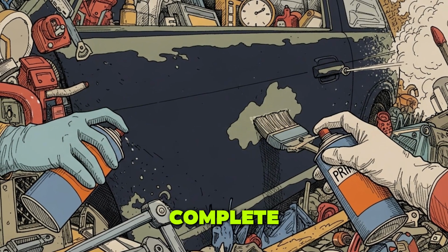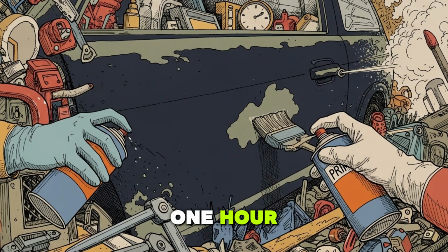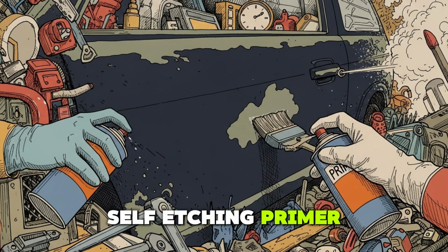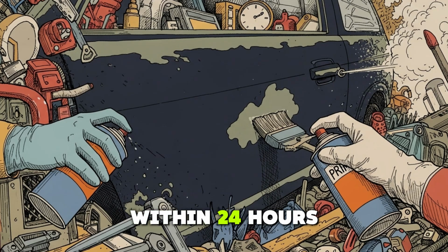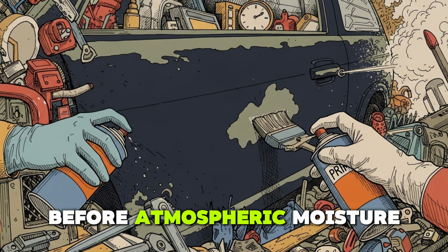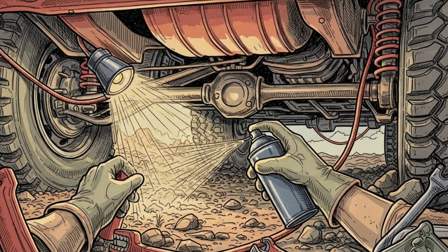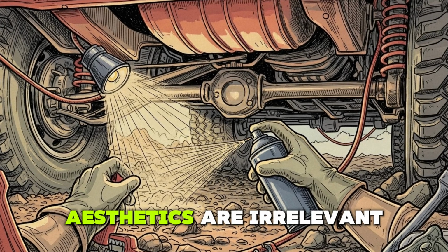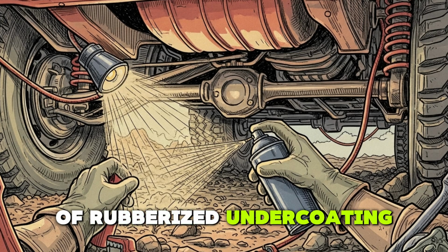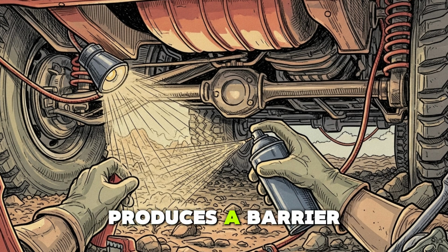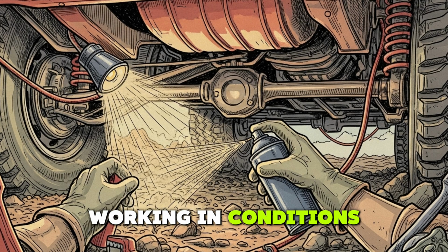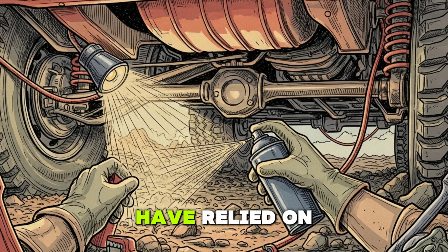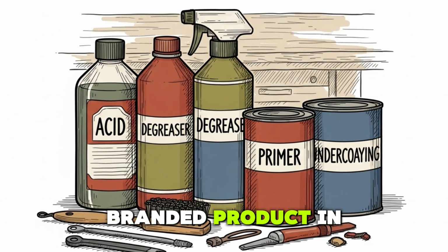After conversion is complete and the surface has cured for a minimum of 1 hour, your finishing options depend entirely on the location. For visible exterior panels, apply a zinc-based self-etching primer directly over the ferric phosphate layer within 24 hours. The phosphate surface has a finite window of peak adhesion before atmospheric moisture begins competing with the primer bond. For undercarriage and frame surfaces where aesthetics are irrelevant, a single coat of rubberized undercoating applied over the cured phosphate layer produces a barrier that field mechanics, working in conditions far more punishing than a suburban driveway, have relied on for decades without a single branded product in sight.